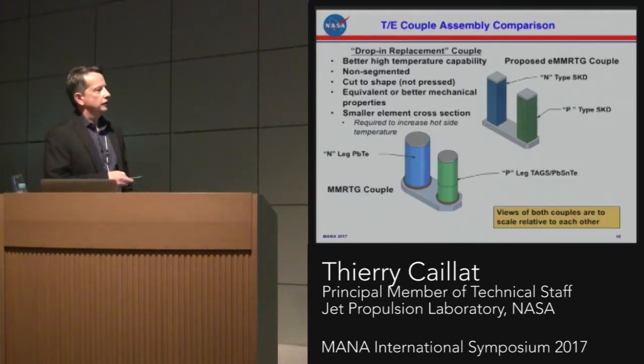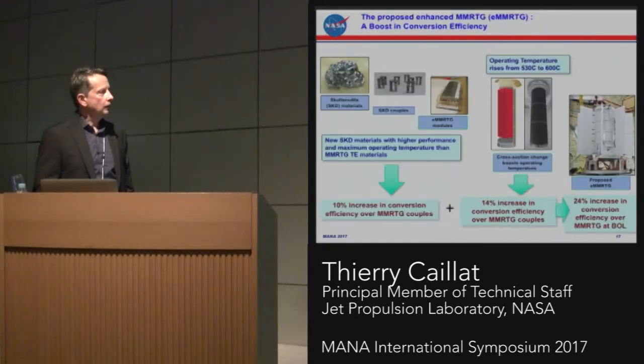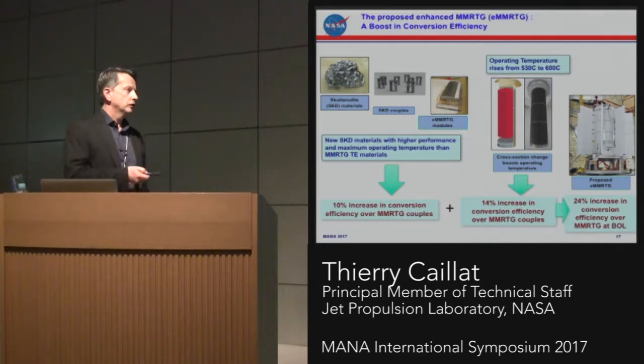This is kind of schematic. We go from round to square for the skutterudite, but this is essentially just for ease of manufacturing, the way the materials are actually prepared. There is nothing special about it. You can go from circular to square materials. So the gain in efficiency that you can get from this, essentially by using the skutterudite materials as opposed to the telluride, you get an increase of about 10% in conversion efficiency. You can also run them at higher temperature, and that boost in delta T results in another additional 14% increase in conversion efficiency, for a total increase at the beginning of life of about 24% in efficiency.